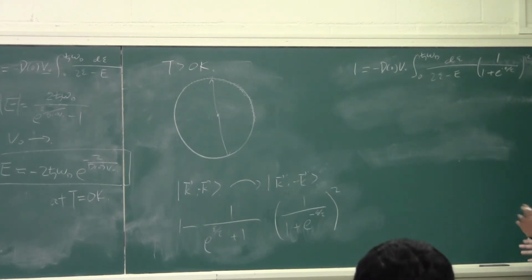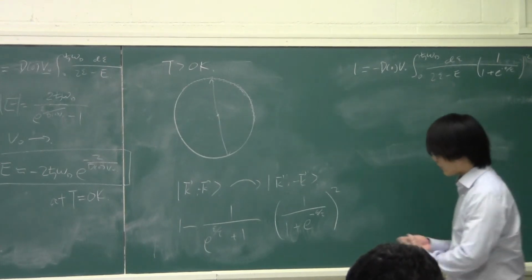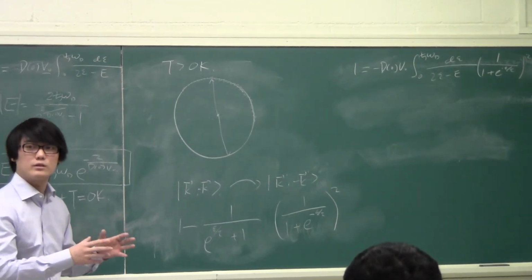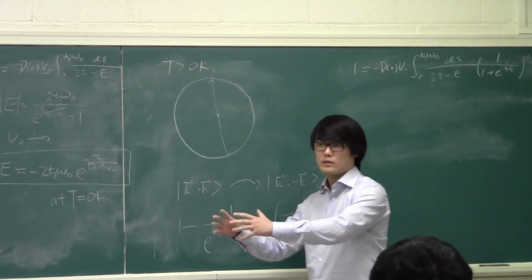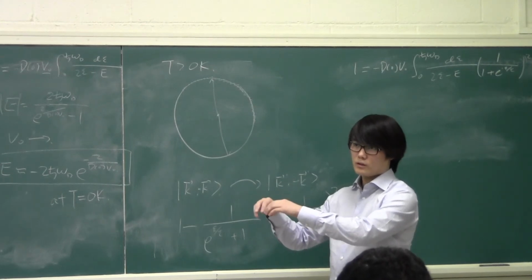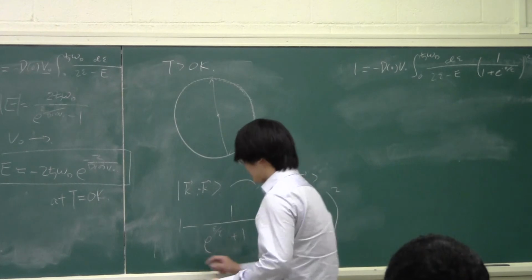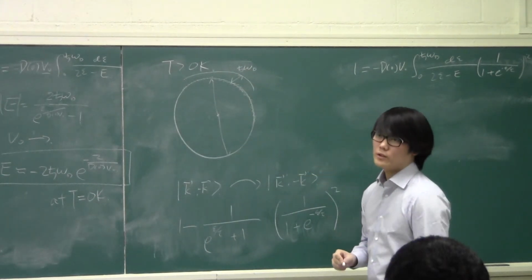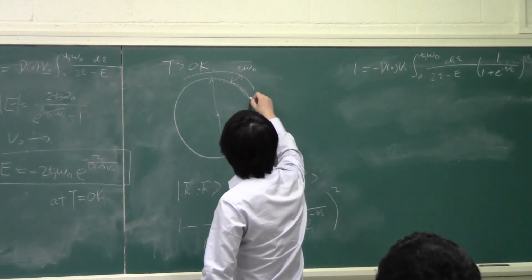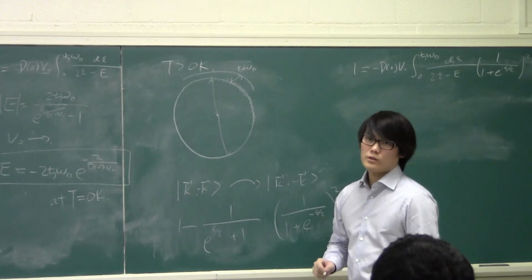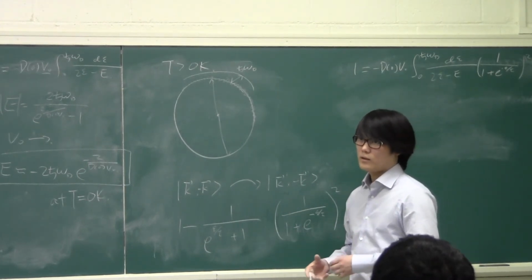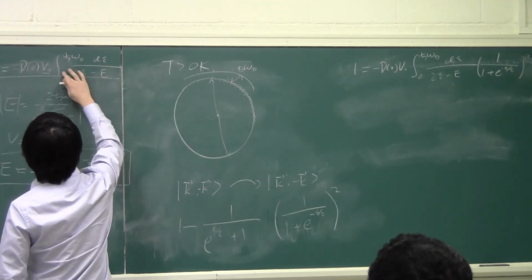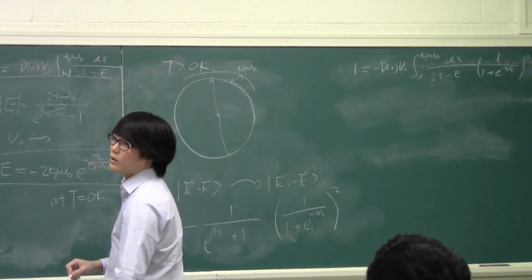Now that integral is too difficult to do. So let's think about what we said before. We say that the presence of this non-zero temperature blurs the originally sharp Fermi sphere. Okay? We can think about this as removing the possible states being linked from the shell over there. So if the shell up to h bar omega D is over here, at a temperature of T, we know that this inner shell is already occupied. So there's no possibility of scattering into these states or removing these states from the picture, right? So that is exactly the same as starting with this original integral and replacing this lower limit just with kBT, right?